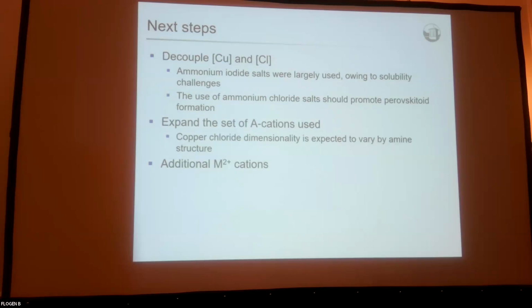So what's the next step, right? So this is the unpublished work in progress. If we have technical hypotheses, we should test our hypotheses. And so the next steps are to decouple copper and chloride and see how that works. In our initial experiments, they were correlated to one another using ammonium iodide salts. That was originally done because of solubility issues. The ammonium chloride salts have a much lower solubility, so we wanted to go with iodide, but going to some of the copper chloride or the ammonium chloride salts should promote the perovskitoid formation more widely.